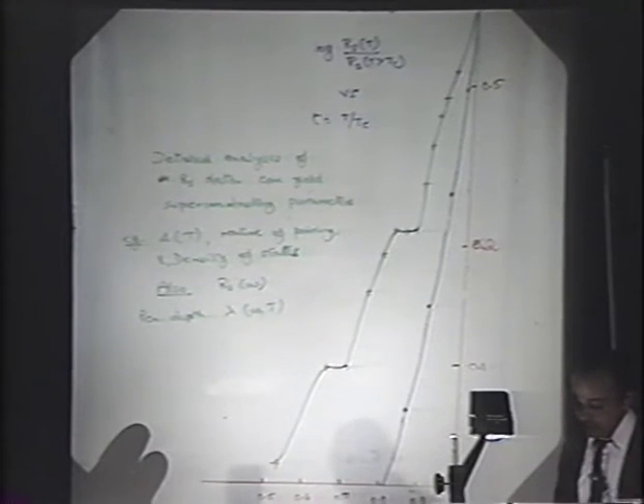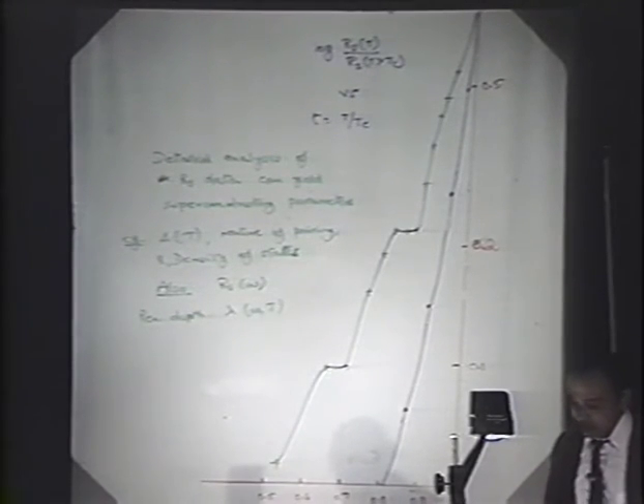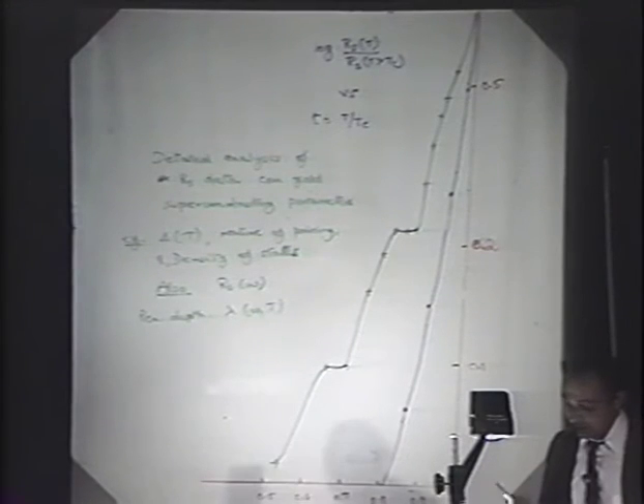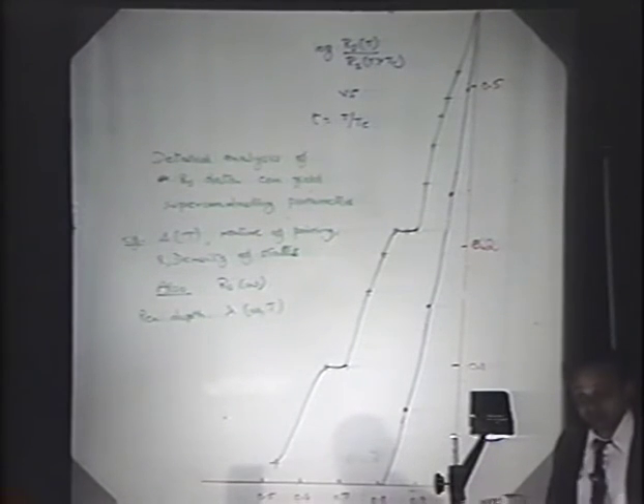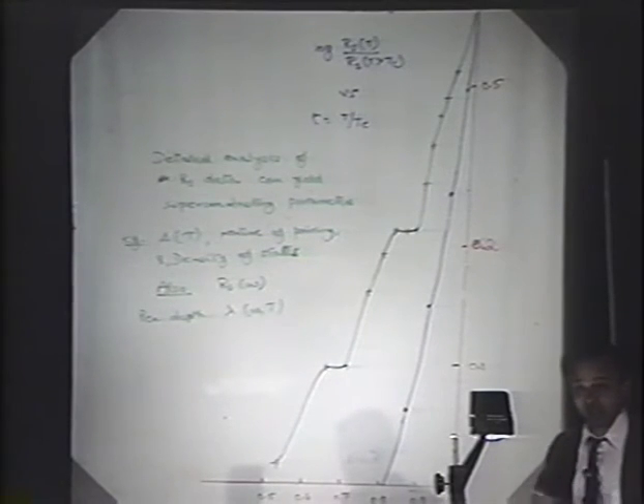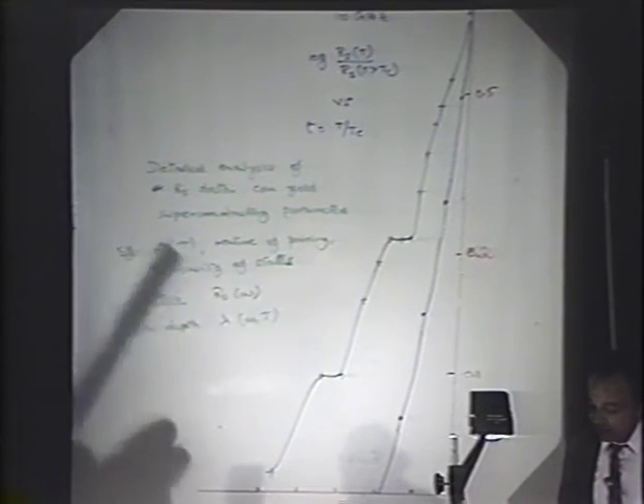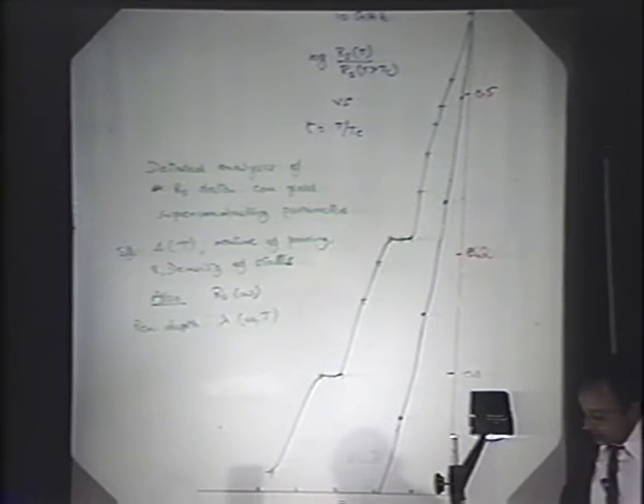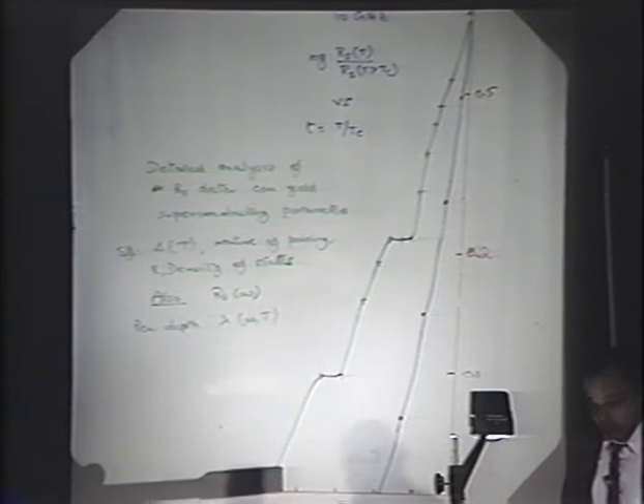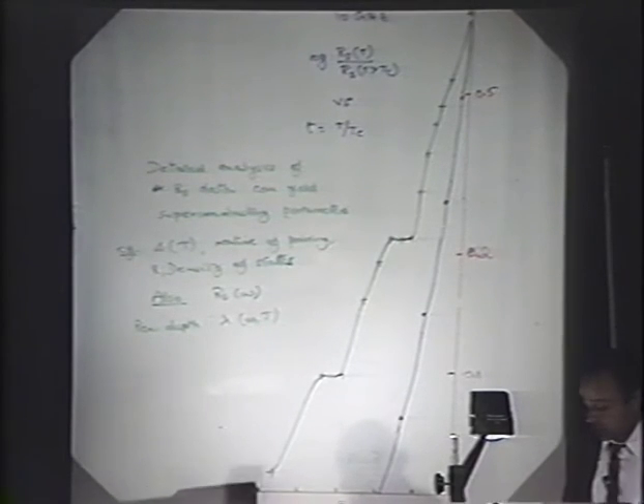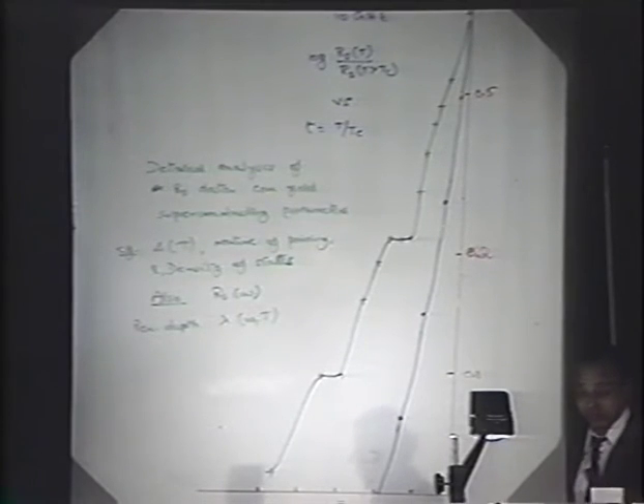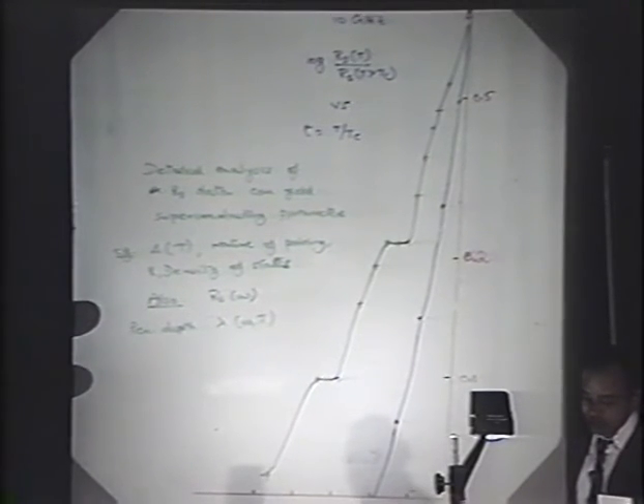Now, I'm trying to fit the experimental data to just taking the BCS form and putting a broad transition on it. I haven't done that yet. The other thing that I'm planning to do is, there's a background, unfortunately, which limits the measurements down to this temperature. I'll try to reduce that over at least a couple of orders of magnitude.